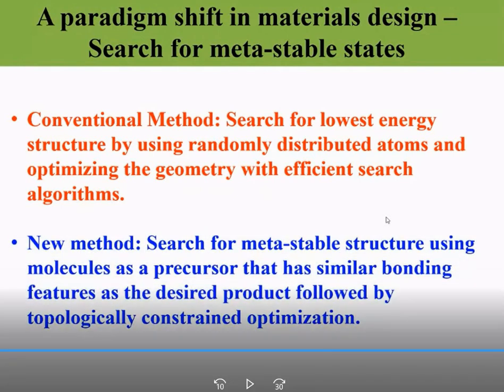One carbon is 4-coordinated and one carbon is 3-coordinated, just like pentagraphene. Then we select a supercell with certain compactness that allows the bonding between all carbon atoms once I dehydrogenate the organic molecule. And then I choose a coordinate system in which I allow all possible orientations to take place in terms of connectivity. And all these things are done using density functional theory.